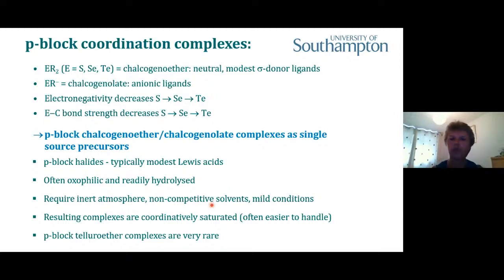We've also got to think about our solvents and the conditions that we use for the reaction chemistry to form the complexes, because if the complexes are relatively fragile or relatively unstable, which on one hand is desirable for the application, we need to be careful that we don't drive that decomposition in an uncontrolled way. So we need to think about using weak donor, non-competitive solvents. We often use things like dichloromethane or acetonitrile as a solvent, and often room temperature or low temperature conditions. It's worth just commenting that prior to that early work that we did, complexes of the main group elements with telluroether ligands in particular were extremely rare.